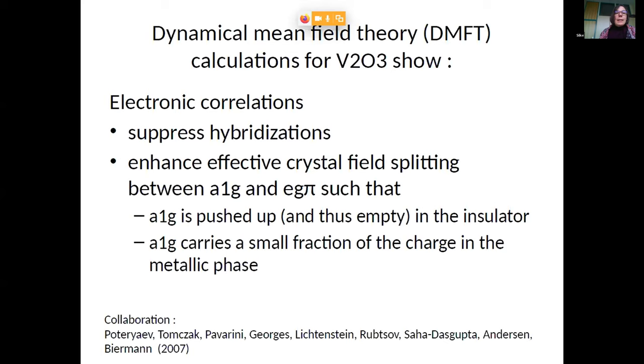So here in this scenario, the compound is in a d2 configuration. And the question is, if the A1G is empty, the EG pi is half filled, it can be insulating. If the A1G goes down, the thing is metallized, and this was actually what was responsible for the metal insulator transition in the calculation.